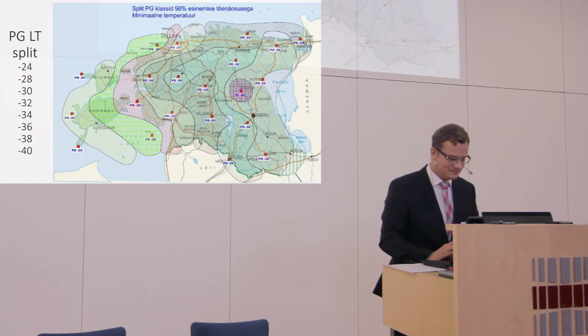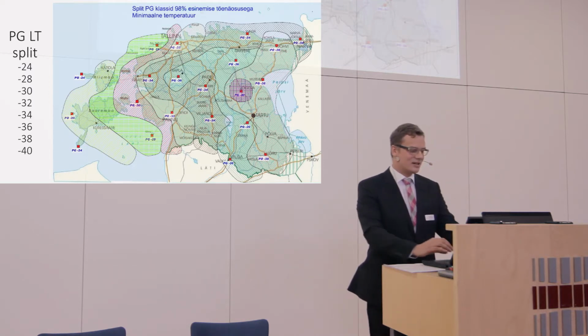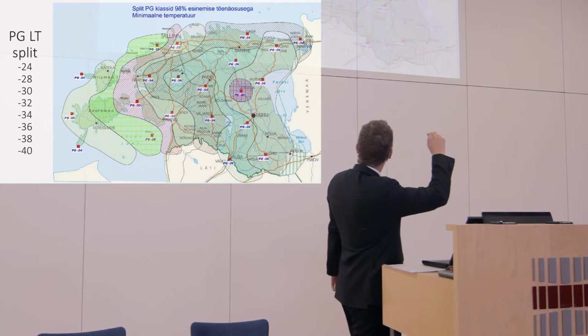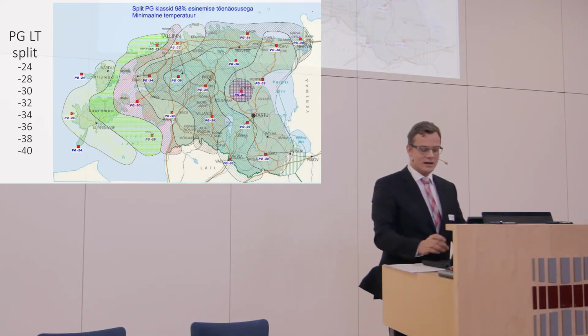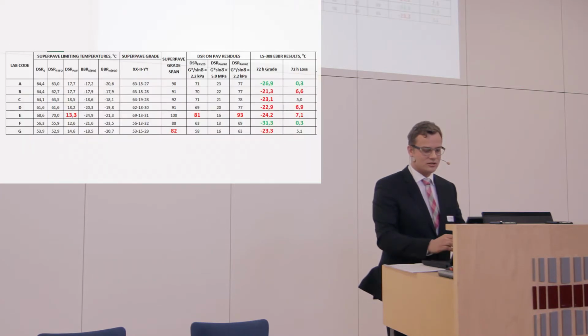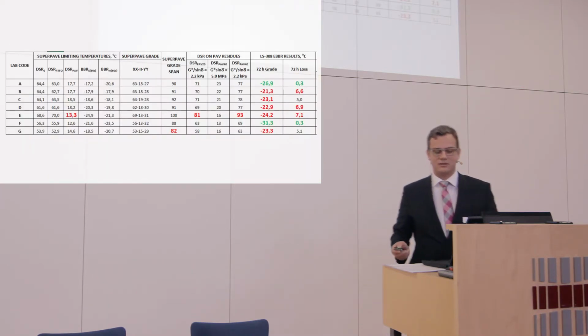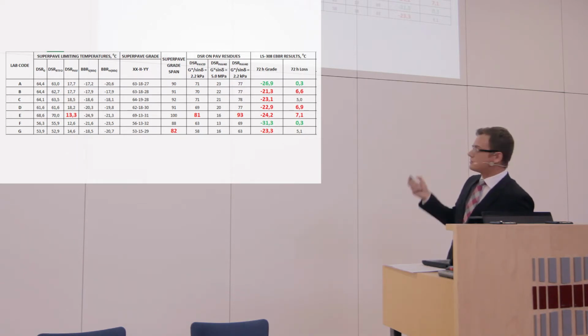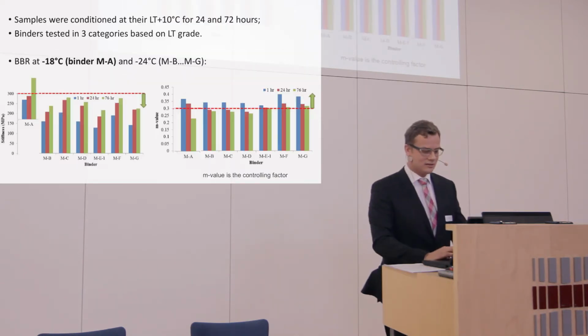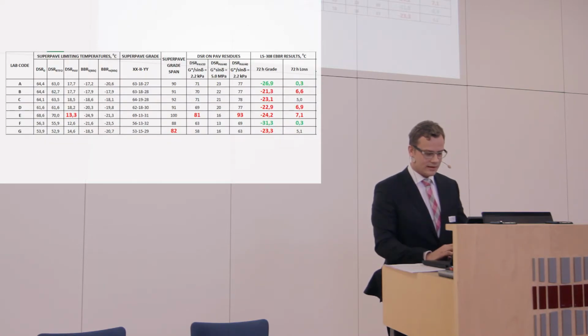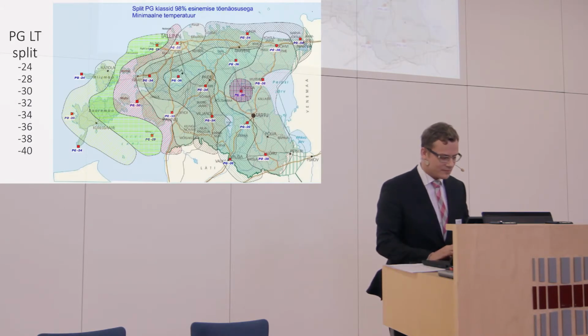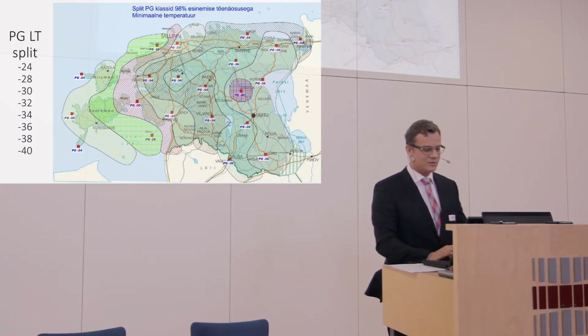You can use that bitumen in this area over here, minus 30 degrees. And when we condition that bitumen for 72 hours, it loses 7.1 degrees, and what's left is minus 24.2 degrees. When you look at this map, it shifted from minus 30 degrees to minus 24 degrees.